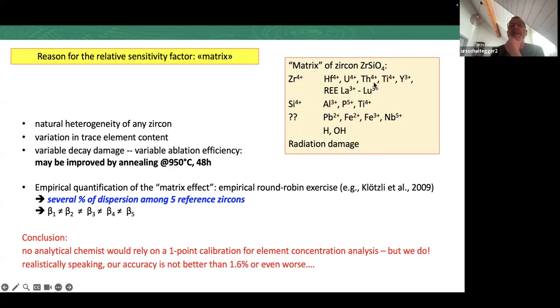So if we want to quantify this matrix effect, we can do empirical round robin exercises. One I'm aware of is Klötzli et al. 2009. They took 5 reference zircons. You take the first one as primary standard, and you measure the 4 other ones as unknowns, and then you go through 2, 3, 4 all around. And the surprise, of course, is that the beta of the first is not equal to the second, third, fourth, and fifth. They report several % of dispersion among these 5 reference zircons, several %.